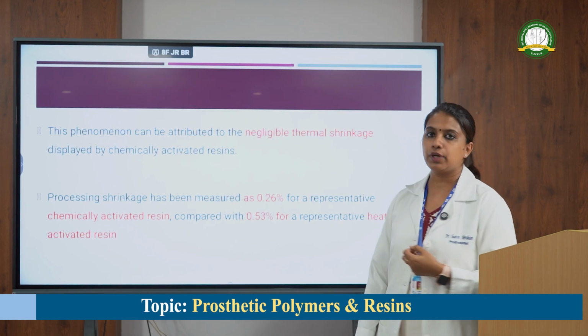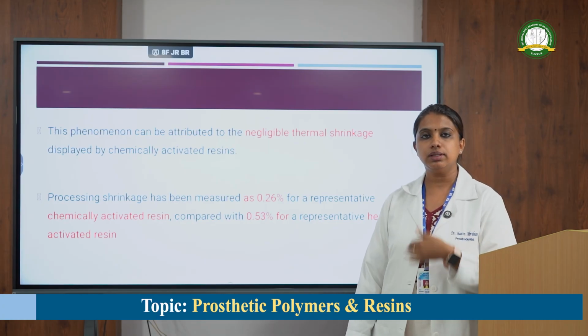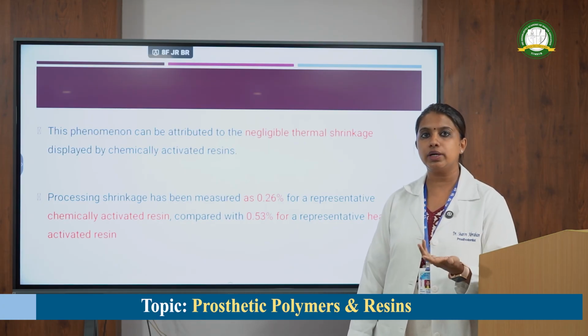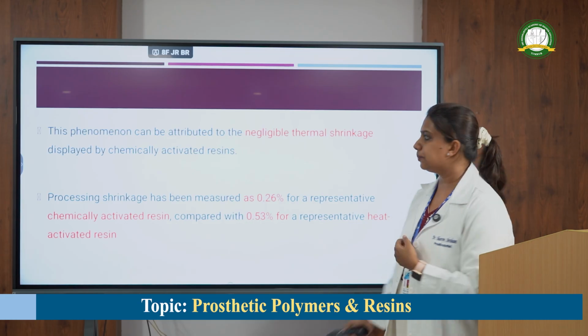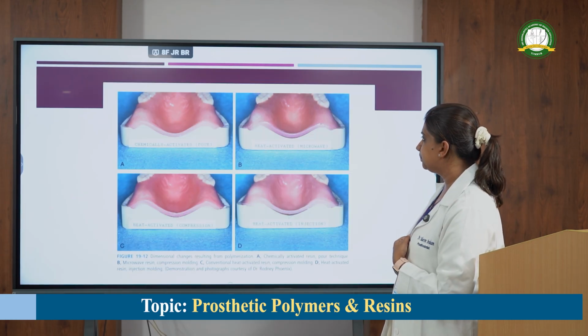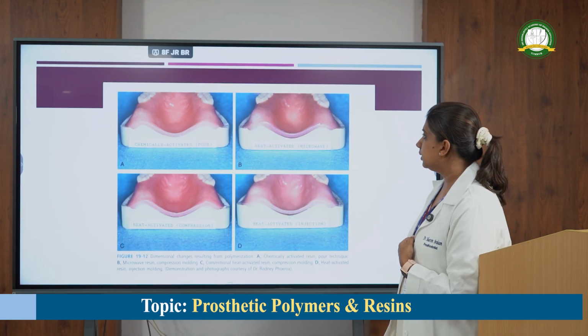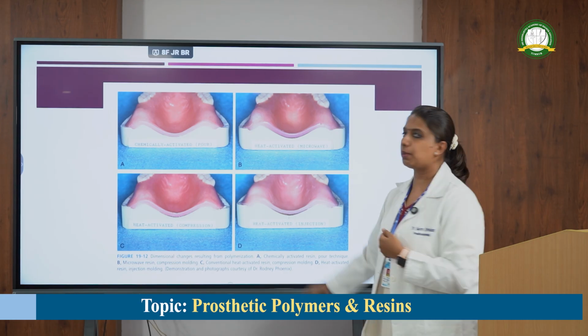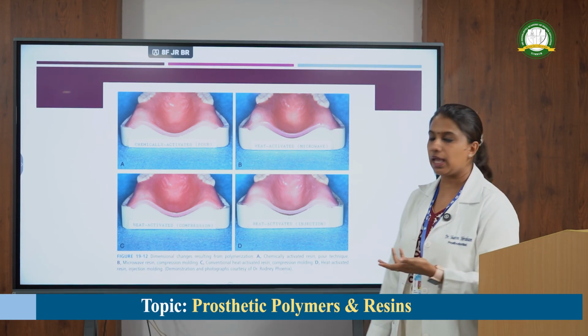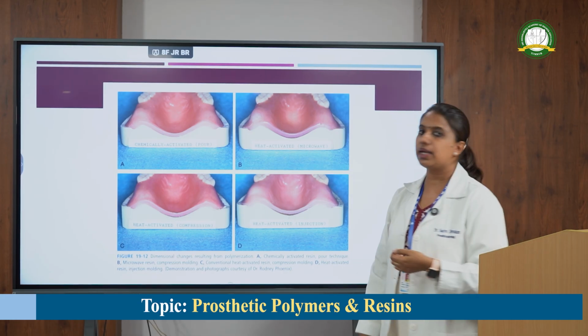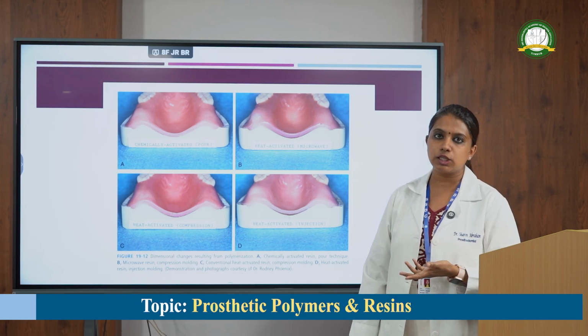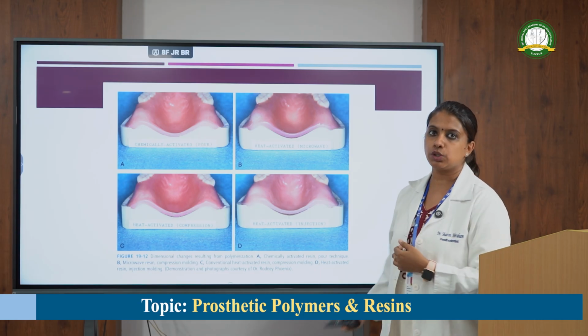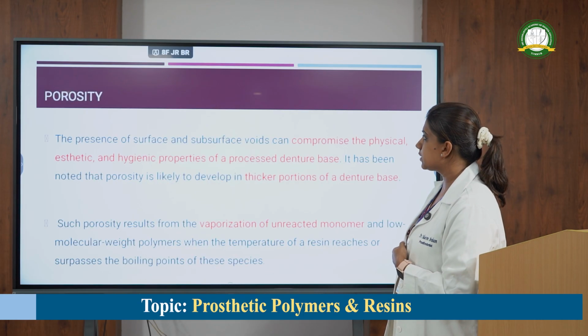Now, because of all this phenomenon, when compared to heat cure, like I've mentioned before, chemically cured has very negligible shrinkage. Like you can see in the picture, in the heat activated resin there is some amount of shrinkage that is very evident, whereas when you check the chemically activated or self-cure resin, there is negligible shrinkage post polymerization or post fabrication of the dentures.